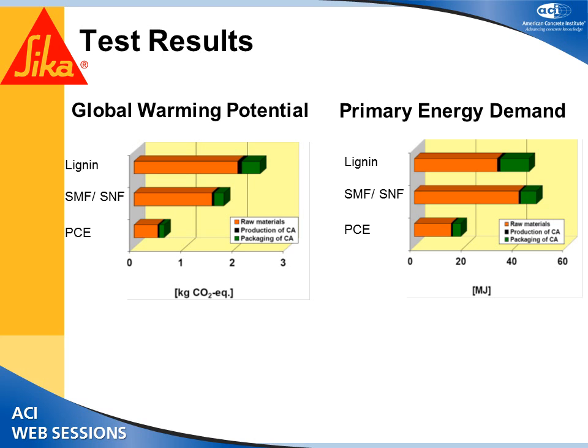Over here you can see even in the green color, the packaging, the PCE is lower as compared to the others, and the reason for that is because PCEs work at a lower dosage, so you require less packing material compared to the other ones. And the primary energy requirement also was significantly lower.